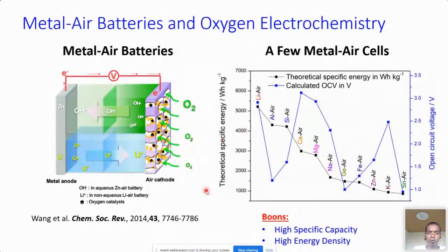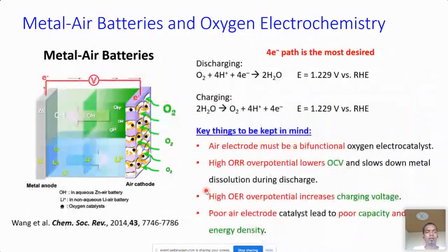So what can we do about it? We know metal air battery depends on both these reactions. This is the discharging reaction and this is the charging reaction, and we have 1.229 volts for both. So what happens if your bifunctional catalyst is not performing this 4 electron reaction, but is performing some other reaction? For example, instead of 4 electron reduction, if it performs 2 electron reduction forming hydrogen peroxide, the standard electrode potential for 2 electron reduction is 0.7 volts, which means the cathodic potential will be 0.7.